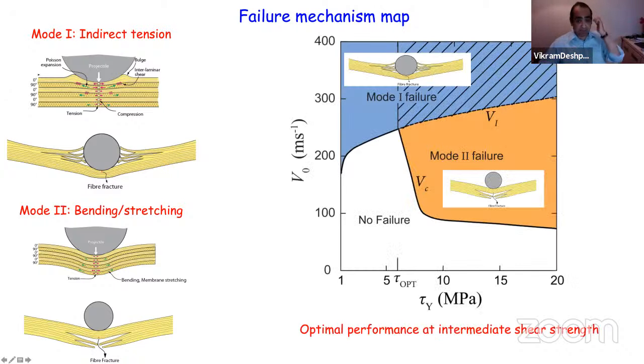And then you can develop a failure mechanism map. This is the failure mechanism map after doing many simulations. And now that starts to tell you that there's something interesting in terms of the shear strength of the beam. There's an optimization here. If you go to very low shear strengths, you get failure here, and no failure here, right? So you want to be in this white regime.